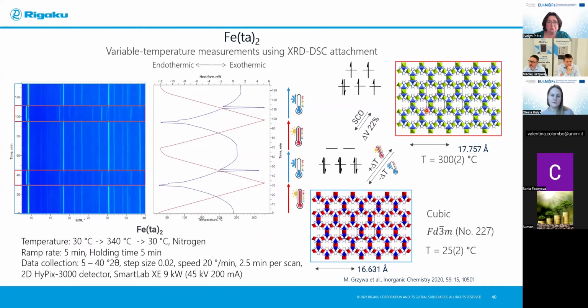This phase transition occurs in the same crystal system and space group, but we observe elongation of the unit cell parameters, as well as an increase of the volume of the unit cell, and we also observe spin crossover in this case. We collected the data here within 5 to 40 degrees two theta. The sample was heated to a maximum of 340 degrees.